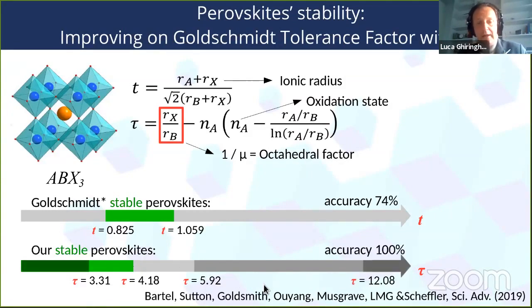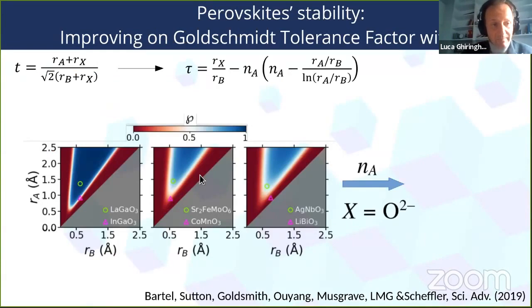So we can construct materials maps like this one. Let's say that we fix the atom X here to oxygen, and we also fix the oxidation number of the big cation. And we explore the space of radii for the two cations. And we see the probability to form a stable perovskite. So zero is low and blue is high. And the plotted data points are those that are confirmed from experiment.